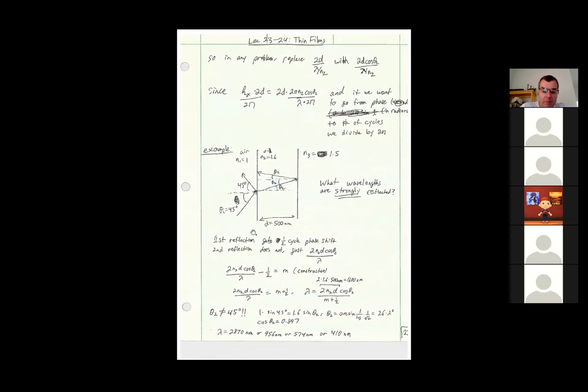Now the thing is, the mistake that people make so often is they think that theta 2 is 45 degrees. But remember, we have to use Snell's law. The light changed direction inside this coating. So we have to use Snell's law. n1, or 1, times sine of 45 degrees equals n2, or 1.6, times the sine of this unknown angle. We solve for that angle. We get 26.2 degrees. So we get the cosine of theta 2 is 0.897. And then we can start plugging in, and we get that lambda is 2n2d times that cosine factor, 0.897, over m plus 1/2. Any questions?